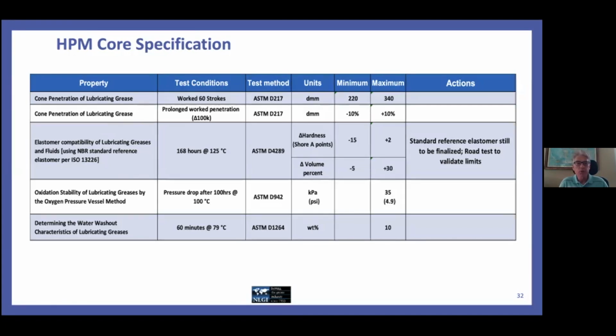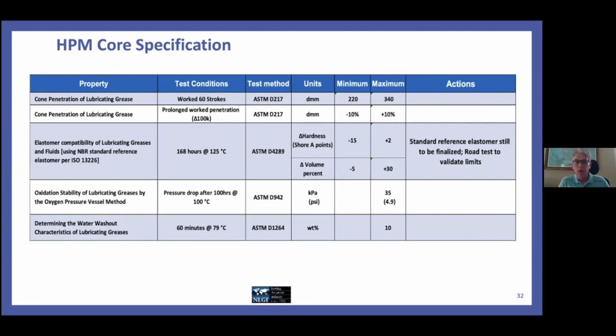Moving on, oxidation stability of greases. This is another one that is not in GCLB today. We landed on the conditions of 100 hours at 100 C pretty quickly. The group was very aligned on this, and the proposed maximum of 35 kPa, which is approximately 4.9 PSI. This was a test where we had pretty good agreement right away and didn't have to work this in a lot of detail. The next one's water washout of lubricating greases.